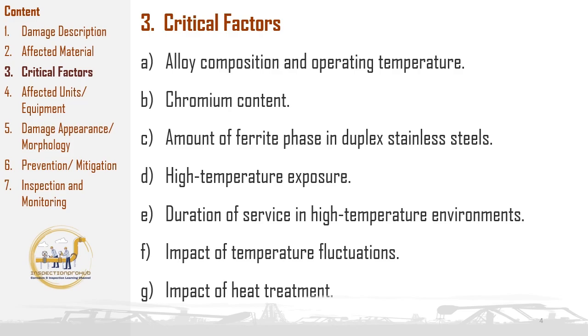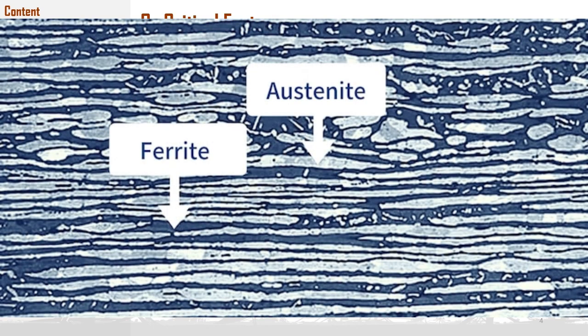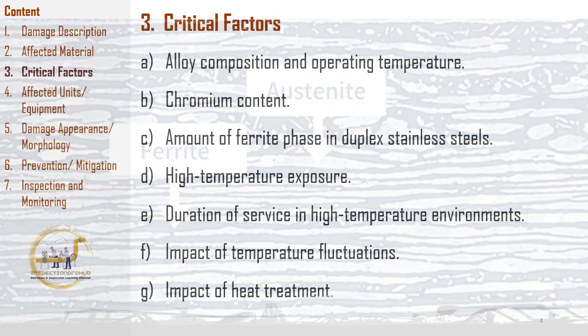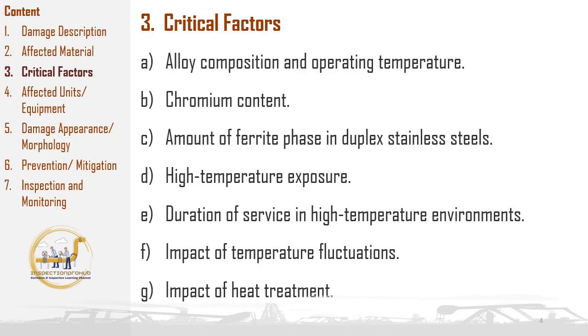Third critical factor is the amount of ferrite phase in duplex stainless steels. The amount of ferrite in duplex stainless steels is a crucial factor influencing their high-temperature performance and susceptibility to embrittlement. As ferrite content increases, the material becomes more vulnerable to damage when exposed to the critical high-temperature range, which raises the ductile-to-brittle transition temperature, making it more prone to brittle fracture.